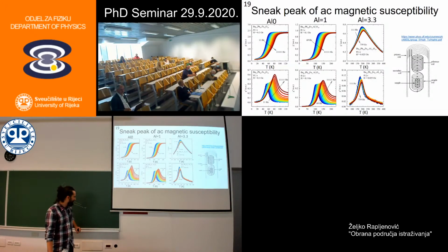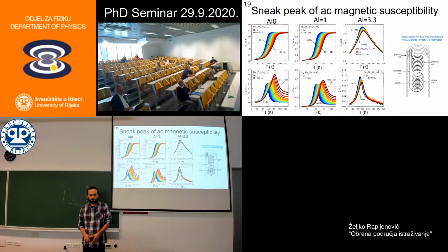If I measure the activation energy depending on the field, I get some crazy large numbers, which upon reducing the amplitude desaturate, and then you get the linear regime. Even 0.1 Oersted is very small. I usually use a much higher field. But this is interesting. It is very small, especially for this last sample. You look at it and it's nonlinear.